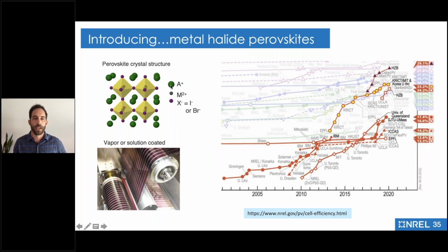It's composed of this A site. So this green atom is typically an organic or a cesium atom that's charged. This metal in the center is a metal 2+. It's in the middle of this yellow octahedra in here. That is either lead or tin or combinations of different metals to achieve the same valence state. Of course, lead is not good, and there's definitely efforts to avoid lead, but lead works the best right now.